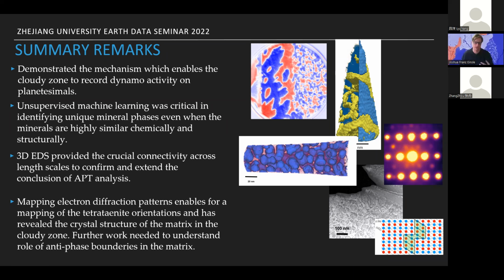So, like in our case here, we have very high resolution data. But even if you look at this atom probe result, the number of grains in that particle is limited by their size. Within that tip, we're able to get like 120 grains of tetrataenite, right? So we have a decent 120 grains.